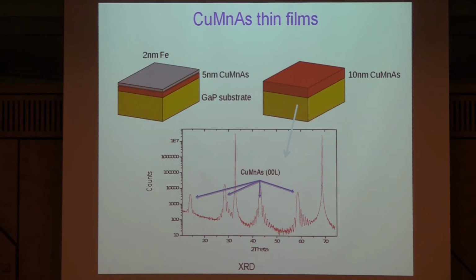Okay? A little bit more, not much now, a couple of slides and I'm done, and then we can all have a cup of coffee. Thin films. We're growing quite thin films now. We can get down to 10, even 5 nanometers. We've grown films with iron on top to look at things like exchange bias and other exchange interactions. It's quite versatile in that respect. The iron grows beautiful single crystal on top of the single crystal of the copper manganese arsenide.